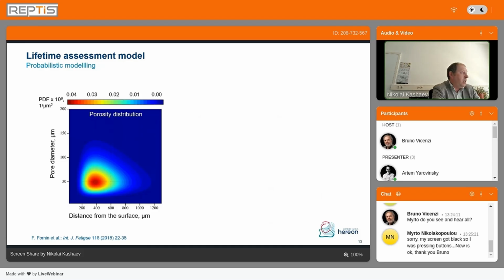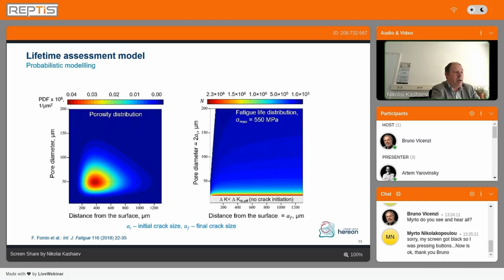Here is our probabilistic modeling, the distribution of porosity with regard to a probability density function. And then we have already our model in principle for each point on this diagram with these axes, pore diameter and distance from the surface. We can calculate the fatigue life of the specimen. Below, where we have our delta K stress intensity factor near the threshold, it means that the pores are less critical, and the possible crack initiation from that kind of pores will result in crack arrest.